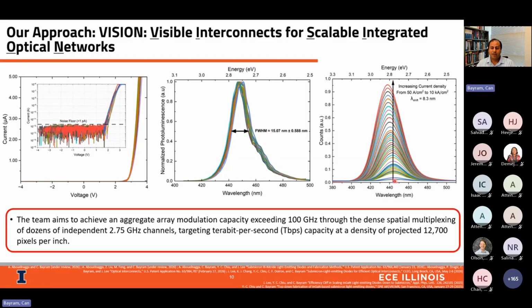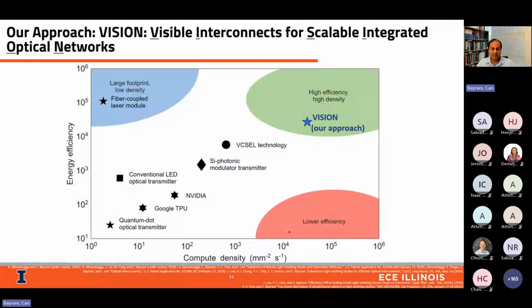And of course, for high power, high speed applications, high injection behavior. And in this case, you can see from going from 50 to 10,000 amps per centimeter squared, the wavelength shift is minimal and the device is behaving very well. So what we project and what we'll continue doing is going into the high density projected arrays for these LEDs so that we can demonstrate a terabit per second capacity in these kinds of scaled elements.